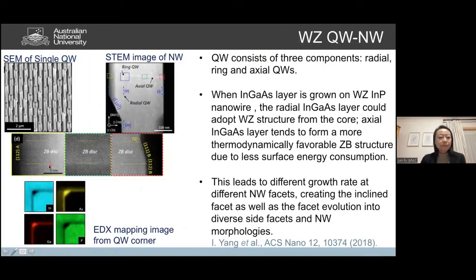So we did that based on our general indium phosphide nanowire growth recipe, and then just switched on the indium gallium arsenide. And we can see that by just growing one thin layer, a few seconds of indium gallium arsenide, the morphology of the nanowires changes from that beautiful hexagonal shape into a very non-uniform structure with a very strange shape on the top, right? So that's very interesting. We don't know whether they're good or not, so we did PL and everything. Looks like we have got quantum wells. I'll show that later on.